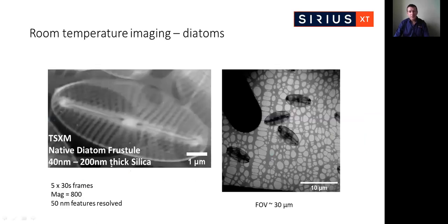For first images of biologically relevant samples, we chose a diatom — 3D structures mainly consisting of silicon dioxide featuring on the nano to micrometer scale. These provide good contrast while remaining transparent, making them suitable test samples for high-resolution tomography without prior preservation. We chose a thin hollow diatom with dimensions of approximately 8 by 4 microns. From measurements of X-ray absorption, we calculate the diatom shell thickness to range from 40 to 200 nanometers. Diatoms were cleaned using a bleach solution, deposited on a standard AC carbon TEM grid, and first imaged using scanning electron microscopy. Images were an average of 5 × 30-second frames, normalized to the flat field, taken at magnification of 800, with good contrast observed over approximately a 30 micrometer field of view with features down to 50 nanometers resolvable.